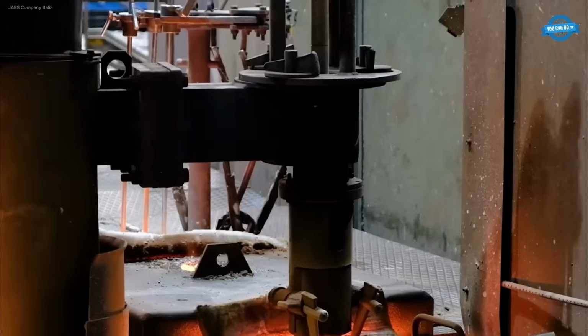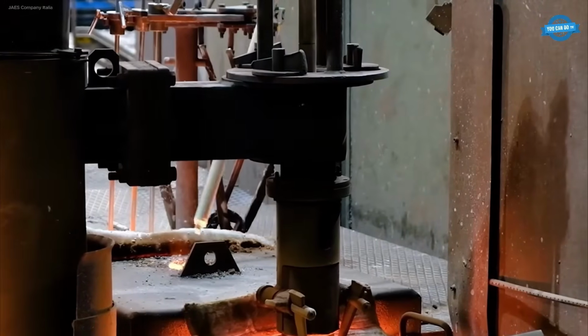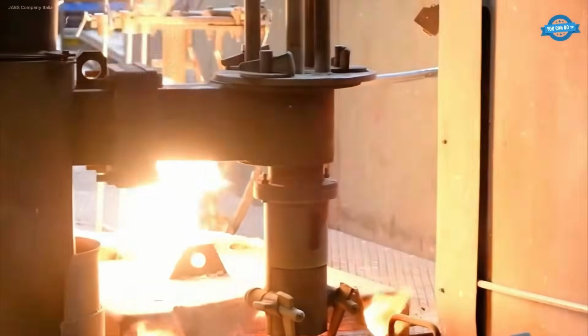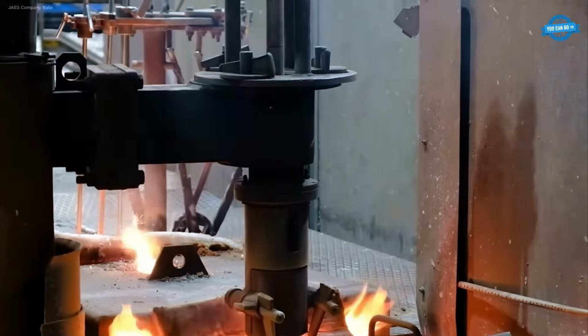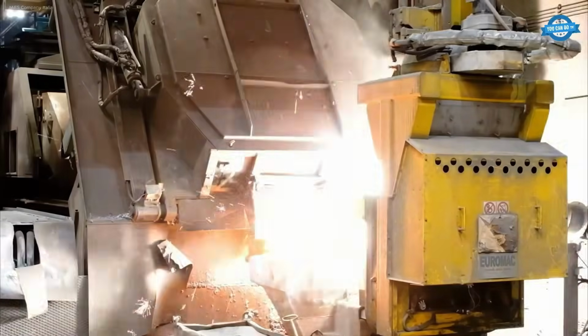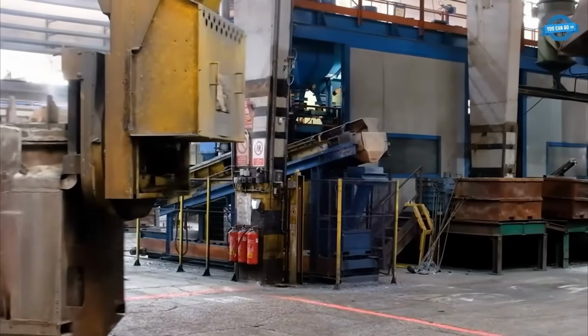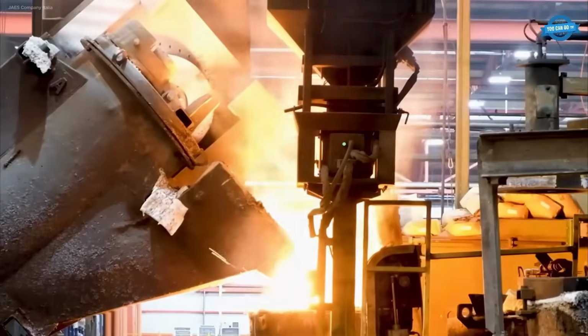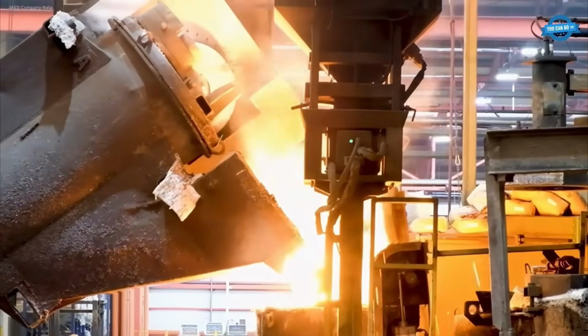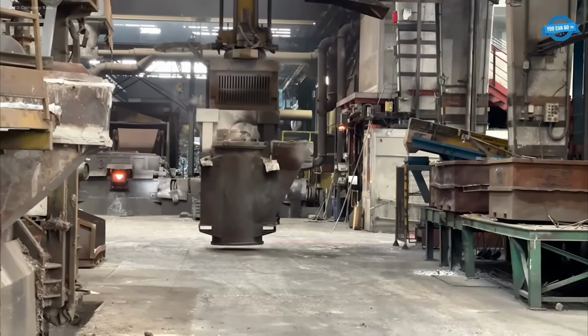After melting, molten iron is transferred into a 3,000 kilogram treatment ladle, where spheroidization takes place through the addition of ferrosilicon magnesium alloys. This violent reaction transforms graphite into spheroidal nodules, improving mechanical properties. The ladle then passes through a secondary cleaning stage to remove slag before the final casting step.